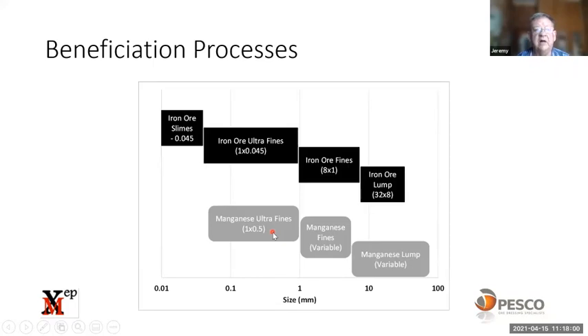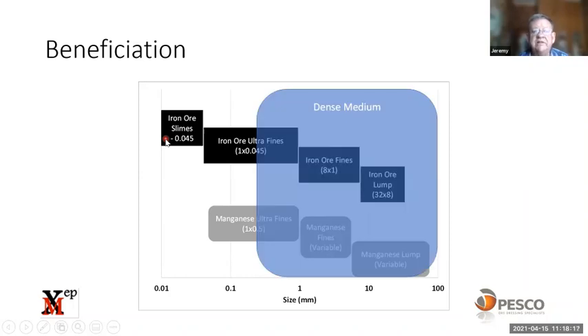If we look at the iron ore, you have lump iron ore, which can be 32 by 8 or 25 by 6. We have fines, which is 8 by 1 or 6 by 1. We have ultrafines, which is the -1 by 45 microns. And then we have the slimes, which is the -45 microns. Dense medium as a beneficiation process covers a size range from 100 down to 0.5 millimeters. So you can see it covers the iron ore lump, the iron ore fines, and a portion of the ultrafines, and that's where more of the development work is, and then manganese, both the lump and the fines.